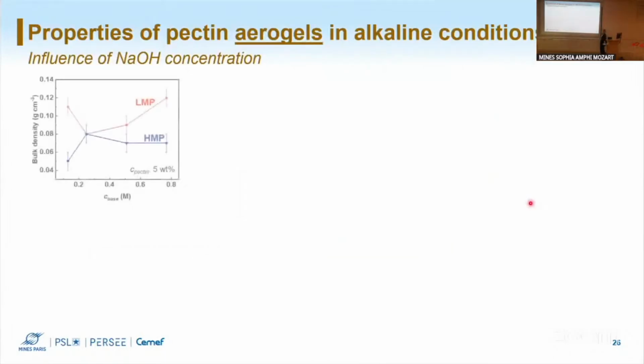So first, we see the properties of the aerogels. Some examples are here. In red on top, there is low methoxypectin, LMP, and in blue high methoxypectin, HMP. And we see that there is not a real trend. The densities are relatively close to each other. They're at low levels.